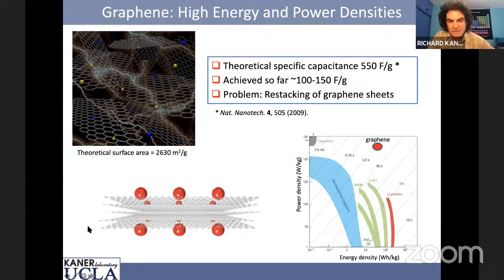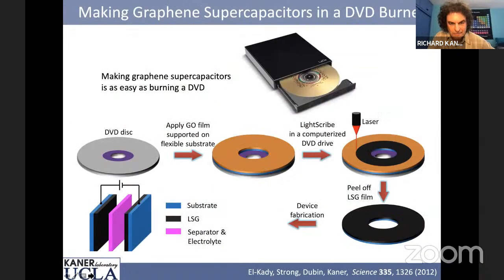And it really has to do with the form of graphene that we're making. It's defective enough that it prevents it from restacking. And that is the whole key. So how do we make our devices? Well, the simplest way is we can take a DVD disc, put a piece of plastic on it, put graphene oxide on, this golden brown material. We can tell our laser to darken the whole thing. And then we can simply peel this off of the disc, and we can put it together and we can make a device.